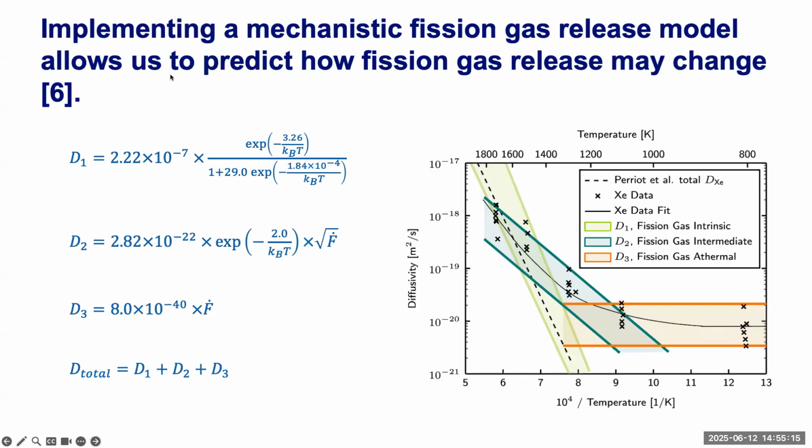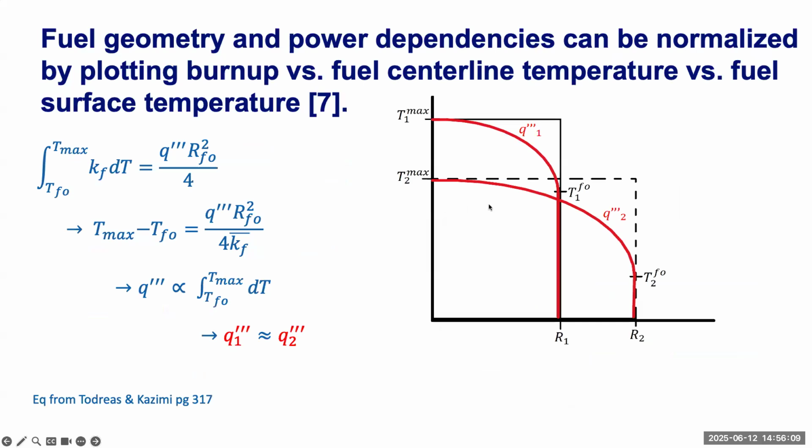The equations that represent these curves here were actually calculated mechanistically using the Centipede MOOSE-based multi-physics object-oriented simulation environment, multi-app structured code. Centipede calculated from information that was produced via DFT, density functional theory, and molecular dynamics calculations, and used information from those calculations to calculate the approximate diffusivity functions for each of these regions. And all of this work that you see presented here was published in a paper focused on xenon diffusivity in UO2 that my mentor at LANL, Dr. Topher Matthews, published.